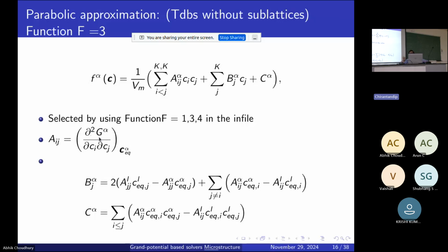have tracked everything that is required with respect to the phase transformation, because the phase transformation in its entirety is most of the time diffusion controlled, and the temperature and composition of the interface is essentially coming out from the Gibbs-Thompson coefficient. We have a Gibbs-Thompson coefficient which sets the correct temperature and composition of the interface. The rest of it is the diffusive mobility of the components in the liquid of the surrounding matrix, and that will come out of the mobilities that we do. But getting the correction to the thermodynamics is precisely this part.